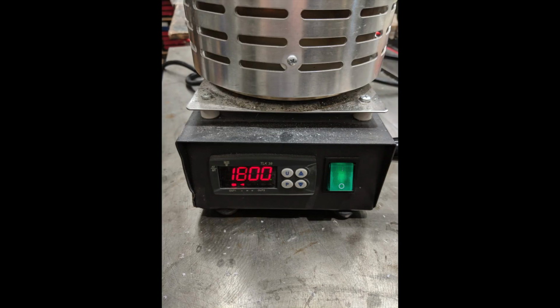There's a chart that you can download at Hoover and Strong which actually lists the casting temperature of gold, which is different than the melting temperature. For the casting temperature of 14 karat yellow gold, I used 1800 degrees in my furnace, and I used a flask temperature of 1,000 degrees due to the complexity of the casting. I set my furnace at 1800 degrees.